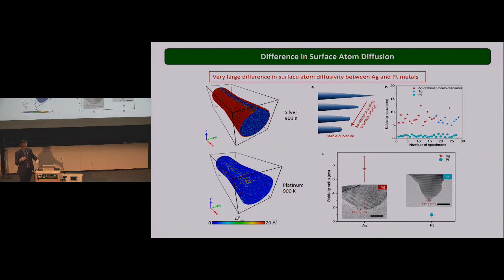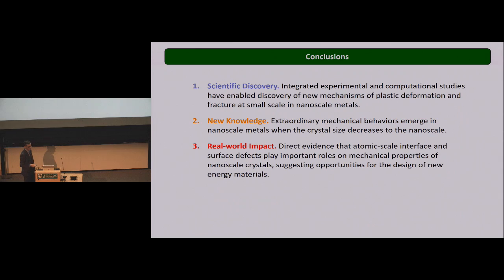And so basically you can measure the diffusivity by just measuring the radius. And so from this experiment, we show that the fact that it's blunt here, more in silver than platinum, is another evidence that the surface diffusion in silver is very important compared to platinum. And that's the source of this difference in mechanical behavior. Okay? All right, so that was the end of the story.